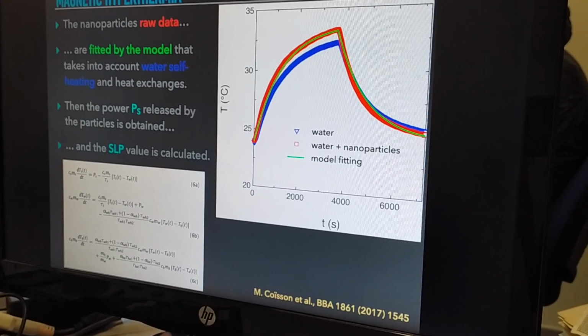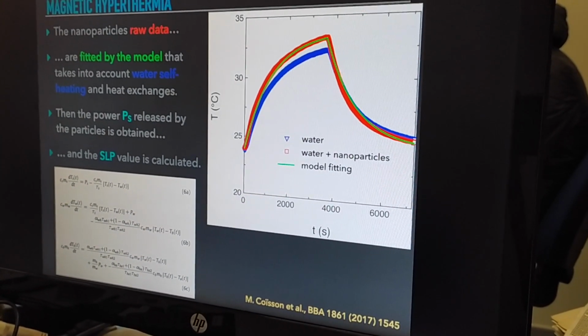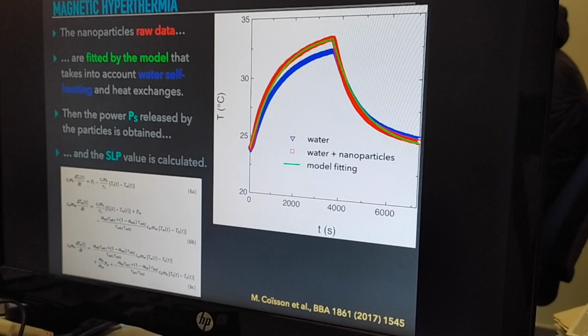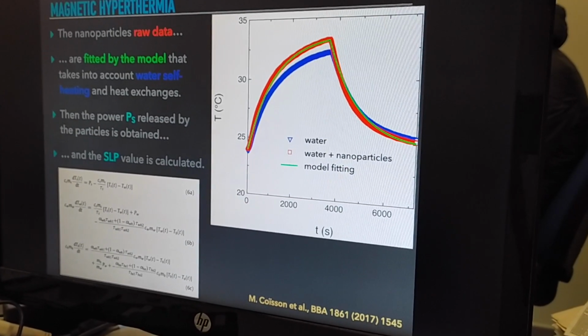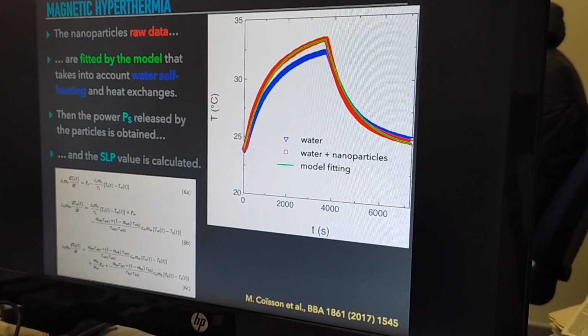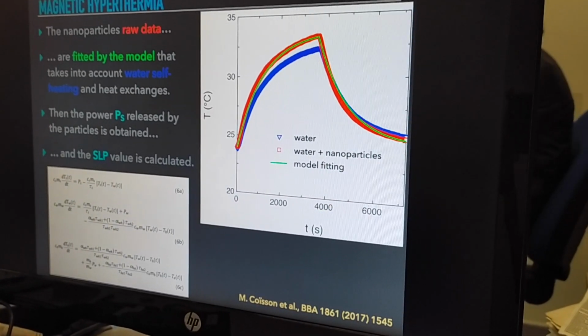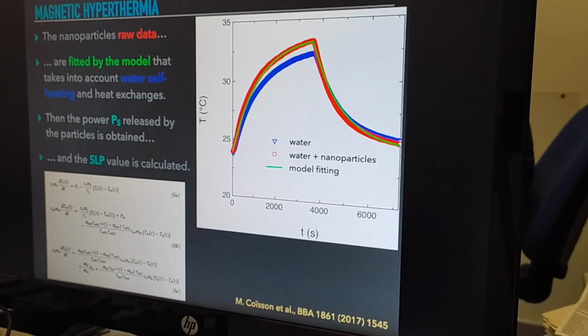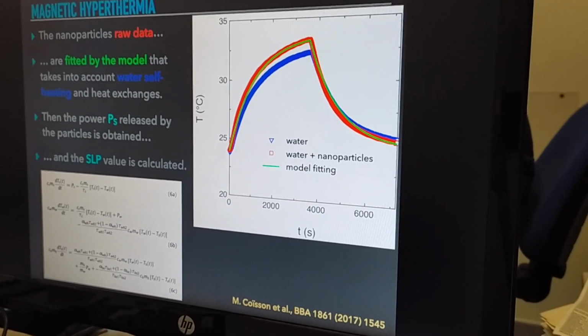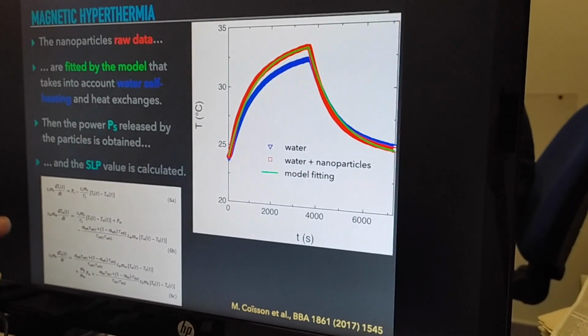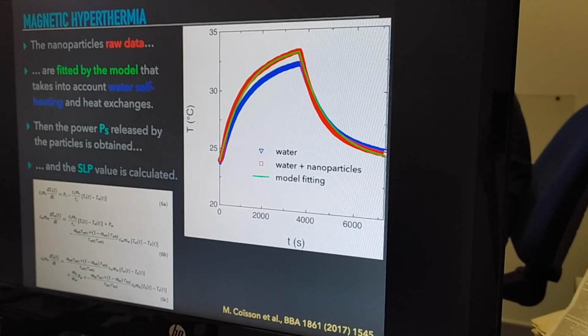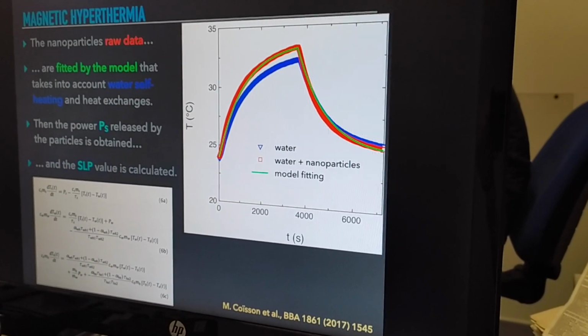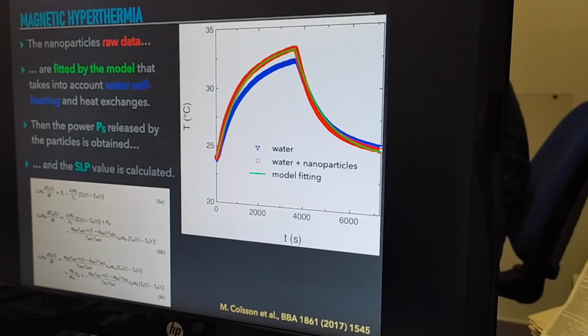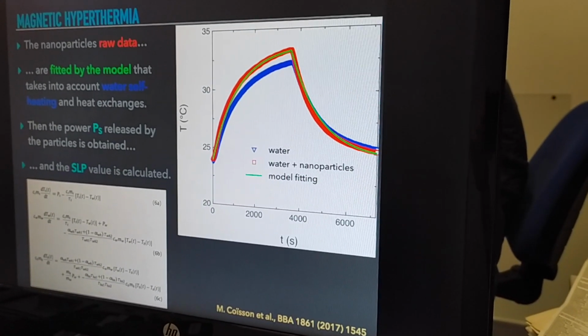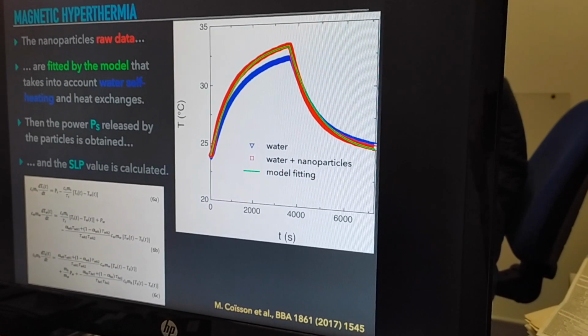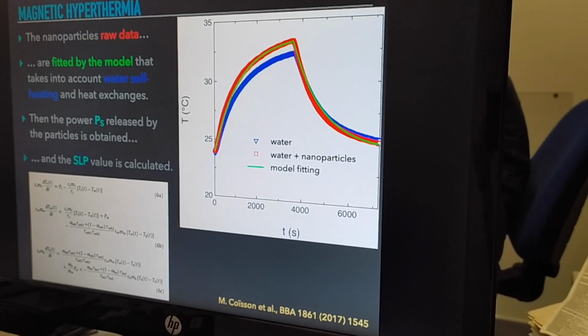This is due to the ionic currents flowing in the water, but also to the thermal exchange between the water and the exciting coil, which of course heats up a little bit during the application of the electromagnetic field. In order to be able to extract the heating power of the nanoparticles, it is necessary to have an accurate model of the thermal exchanges between the different components of the system, namely the particles, the water in which they are dispersed, and the surrounding environment, through a suitable set of differential equations.